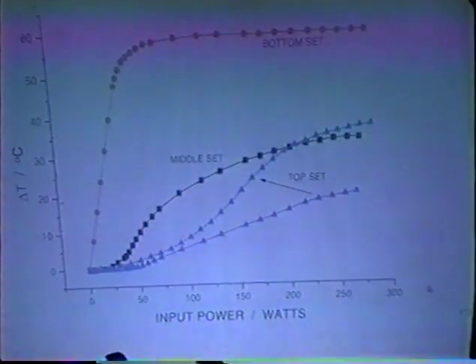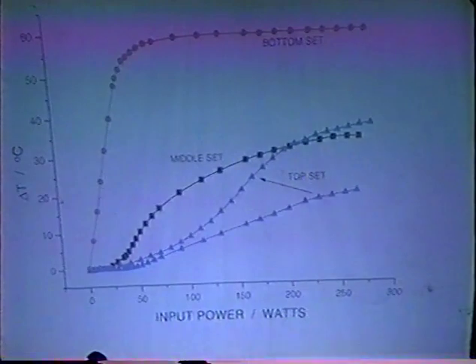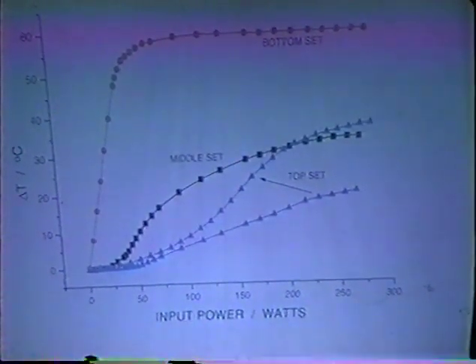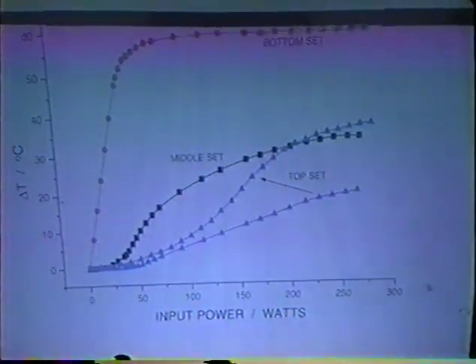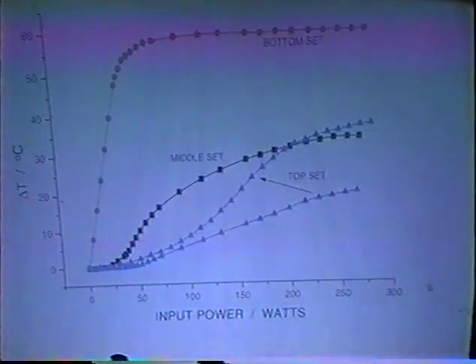As you put power into the calorimeter, the temperature for the lower set goes up almost linearly. When you start to get up near, in this particular example, 50 or 60 watts, the temperature approaches boiling. And of course, no matter how much power you put into the calorimeter at that point, you will always measure a temperature difference according to this horizontal line here, because you cannot raise the temperature of the vapor higher than the boiling point.